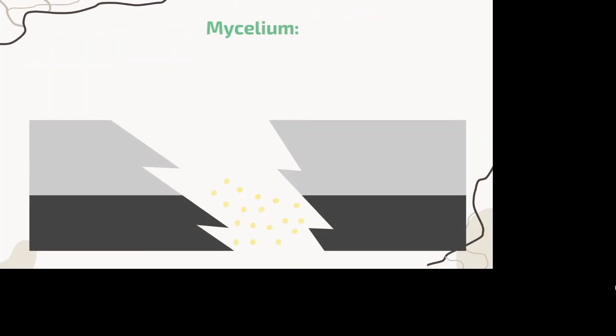Eventually, when a crack appears in concrete, it will be filled by water due to rain. At that moment, the dormant fungal spores will germinate and act as a catalyst to produce calcium-carbonate crystals. This crystal will then grow to the point where the crack is completely filled. This will cause the fungi to become dormant again and release new spores. If the crack is reopened, the dormant spores will germinate again and fill the crack repeatedly, making it a self-healing process that can go on over and over again.